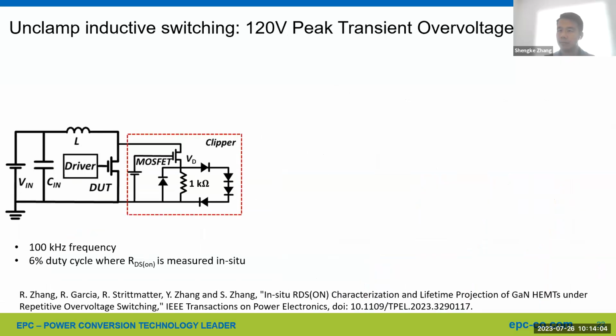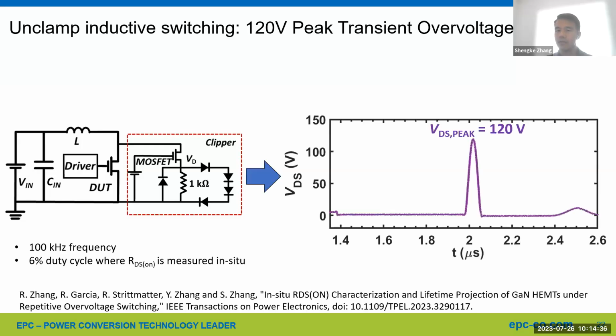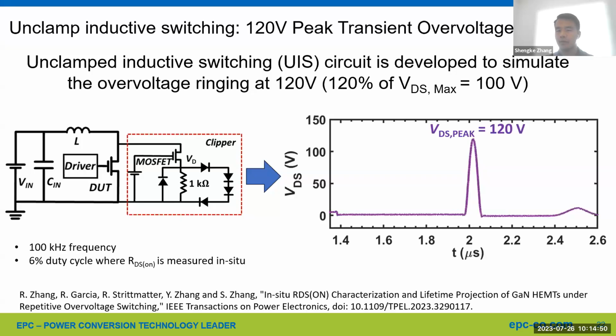Okay, so now the next step is to emulate the over voltage ring effect. So we developed this unclamped inductive switching test circuit, as shown in this schematic, where we can also conduct in situ RDS monitoring to see how the RDS changes over time under these 120 volt repetitive over voltage spikes. On the right is the resulting 120 volt peak over voltage waveform that is produced by this unclamped inductive switching circuit. Therefore, the DUT overvoltage ring can be simulated by this UIS test circuit.